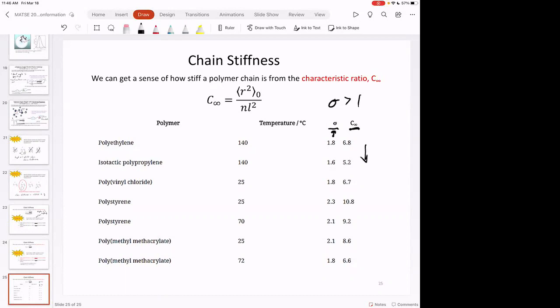Good. And so this is what the table looks like. You see the chain stiffness parameter, sigma, and then you see our characteristic ratio. And in general, they follow each other. They're measured slightly different ways, but it's the trend that's really important. So you see polystyrene here has a large steric parameter and a large characteristic ratio. Something like polyethylene has a smaller steric parameter and a smaller characteristic ratio.